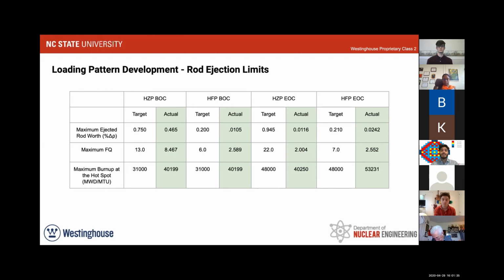However, we exceeded the maximum burnup at the hotspot for some of these scenarios, and the reason for that is because we have a highly enriched core. If we were allowed to increase some of the target limits for the rod ejection limits, like we did with the nominal maximum burnup, we could easily meet the maximum burnup at the hotspot with this core. Next slide, please.